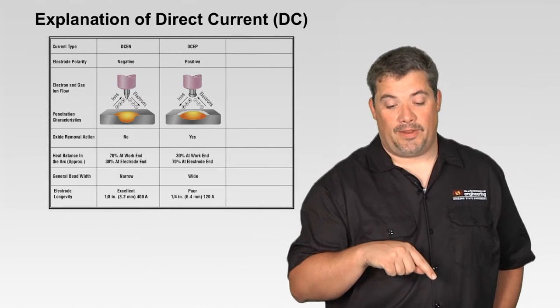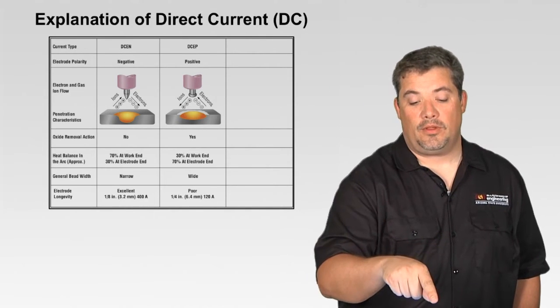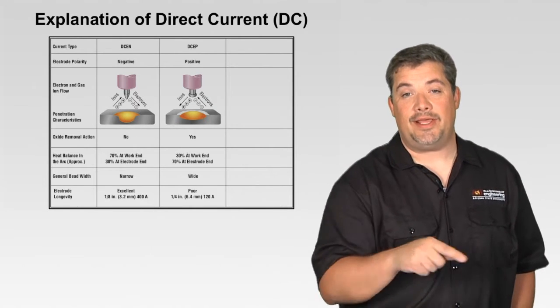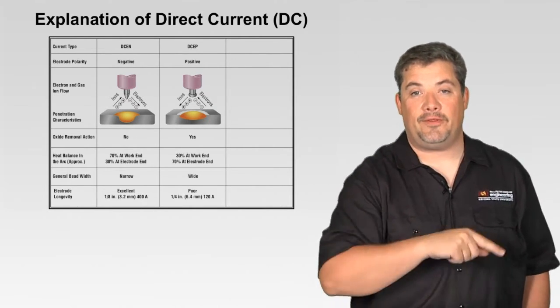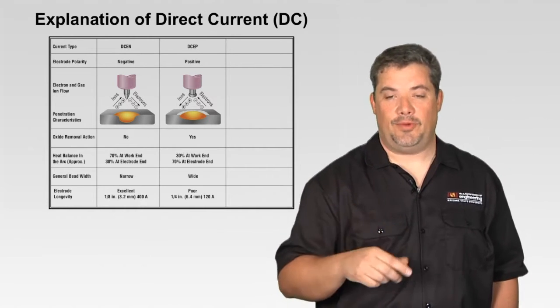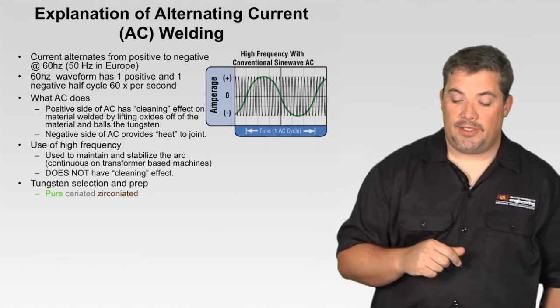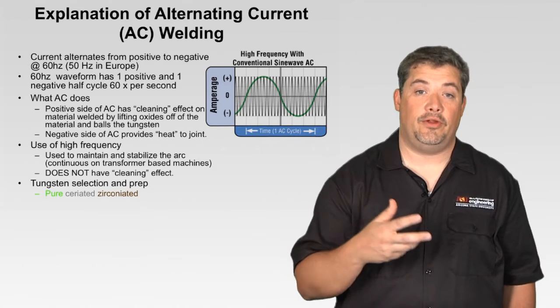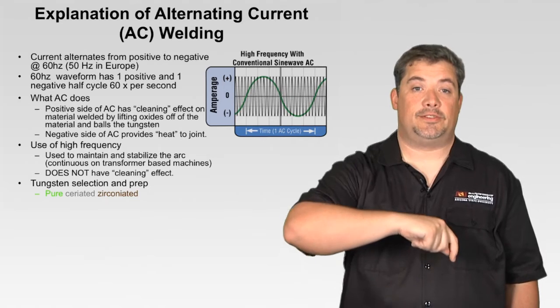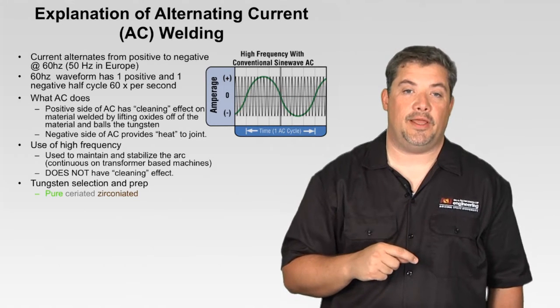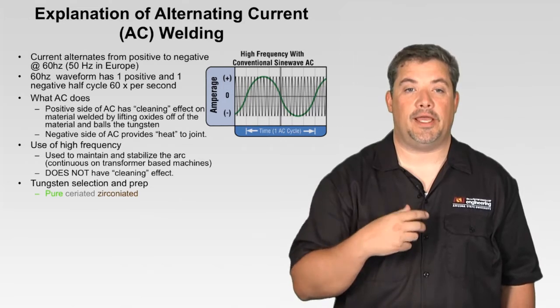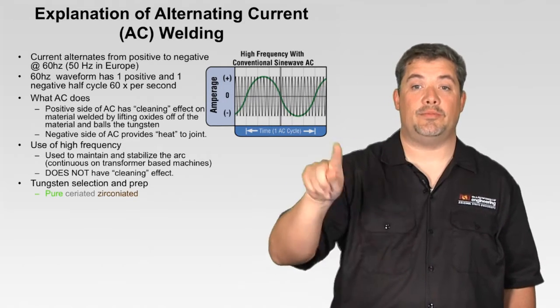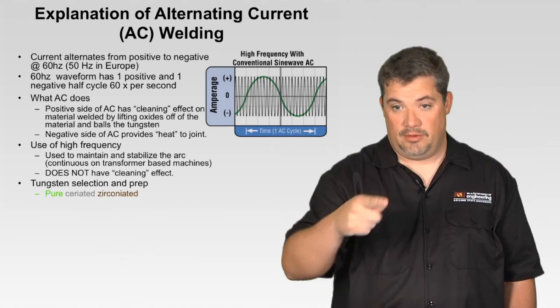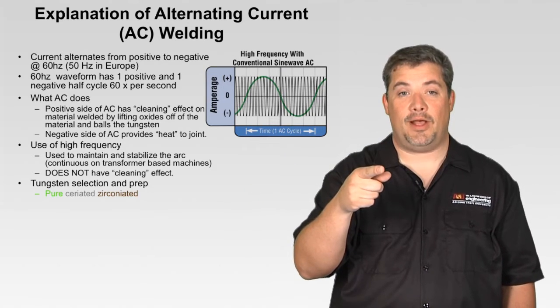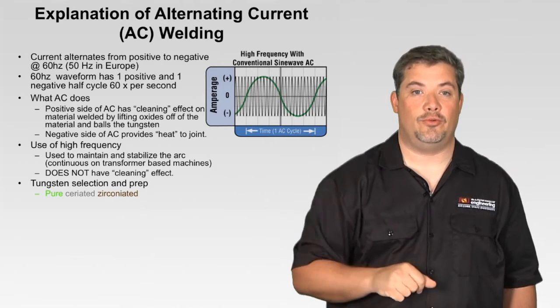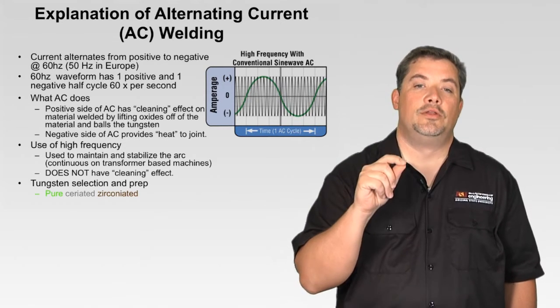So backing up quick to that slide, the difference between electrode negative and electrode positive, well, that's actually AC, because half the time it's negative, half the time it's positive. That's essentially what AC is. So current alternates from positive to negative 60 hertz, or 50 hertz in Europe. So that means basically one positive and one negative cycle 60 times per second. So it literally changes 120 times per second, right? Because 60 positive, 60 negative equals 120 changes. And that's per second.